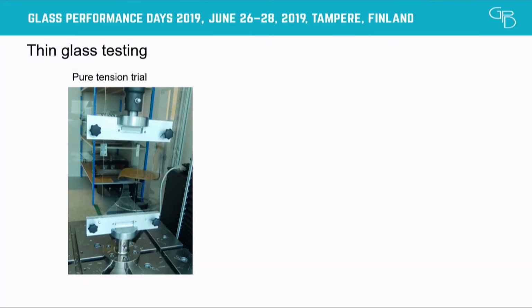And I could create a sort of dog bone-shaped specimen. To describe it in more detail, this specimen here clearly is transparent. So essentially, there is a space where I have a slot cut inside my glass. And then in this central part is where I want my glass to break, and this is the same slot at the top. So I'm doing a very simple tensile test.